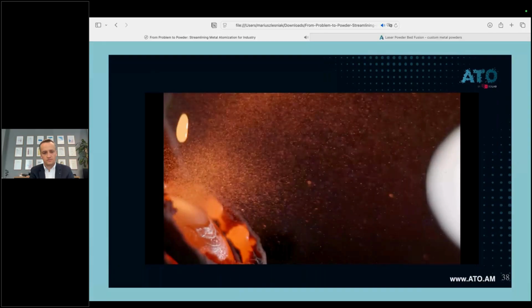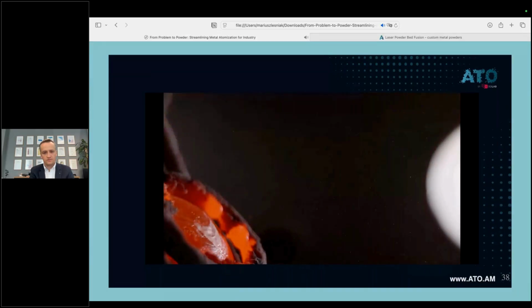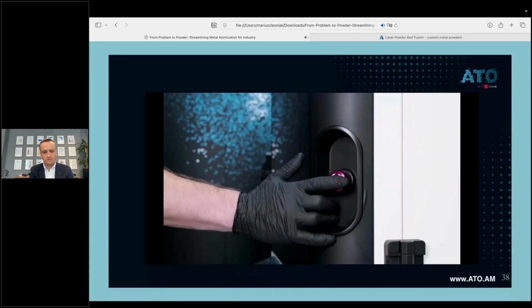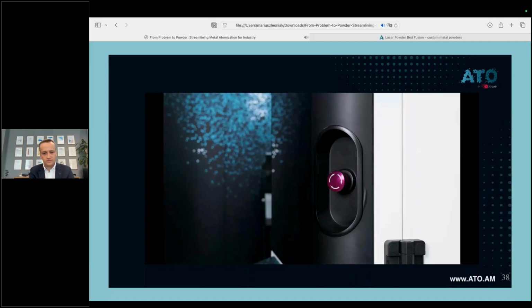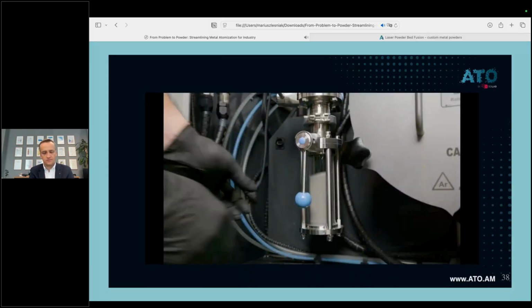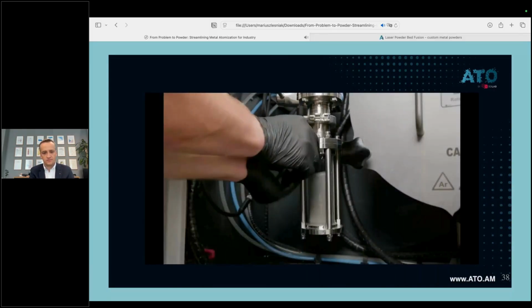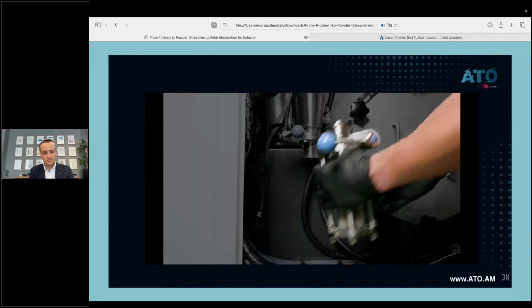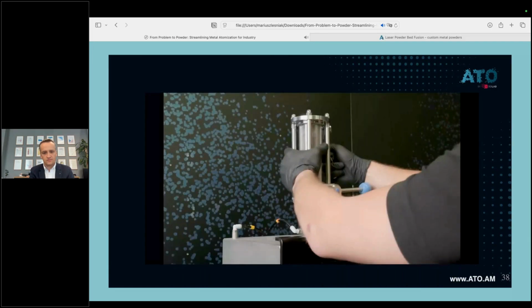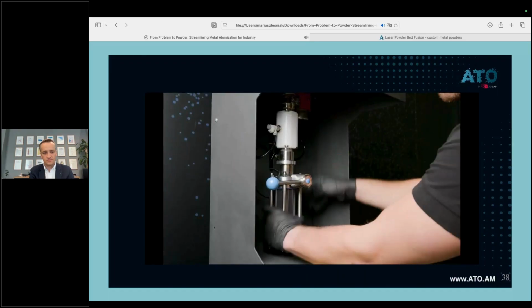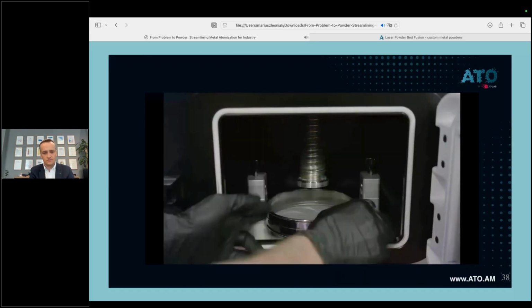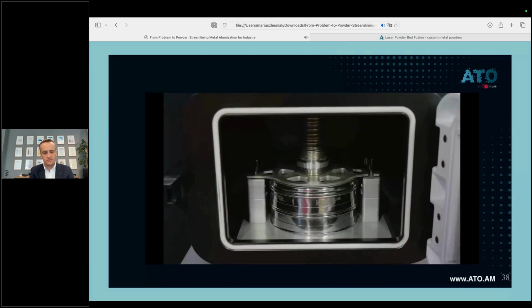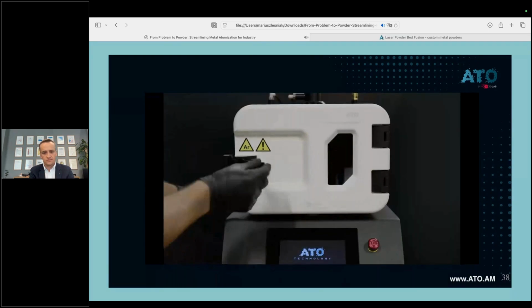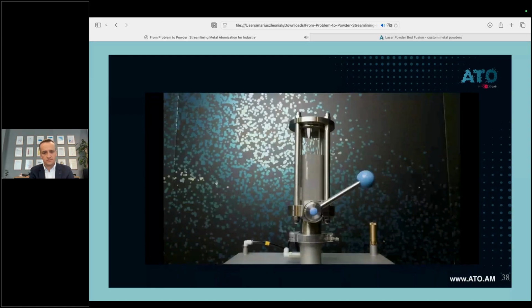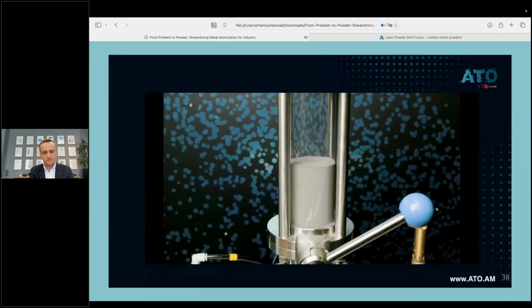When atomization is done, turn off the atomizer with one click and collect the produced powder. Our universal sealed powder container keeps material in an inert gas atmosphere to protect from oxidation. Use the ATO sieve to separate powder by size and make it ready to use. It's an ultrasonic sieving station with a sealed chamber in inert gas atmosphere. Ultrasonic vibration prevents clogging and boosts sieving performance. Efficient, clean, and consistent. Sieving made easy.